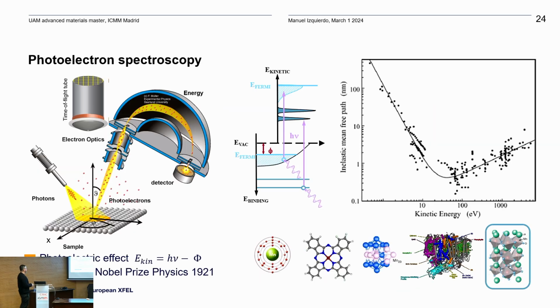So the technique that we have started implementing is time-resolved photoelectron spectroscopy on solids. Unlike what we have seen at SCS, this is a photon-in, electron-out technique. It's also based on the photoelectric effect that gave Einstein the Nobel Prize in 1921. What you can do is analyze the photoelectrons as a function of the kinetic energy, of the angle, of the spin, and from there you can get very detailed information about all the properties of your material with the same sampling depth.